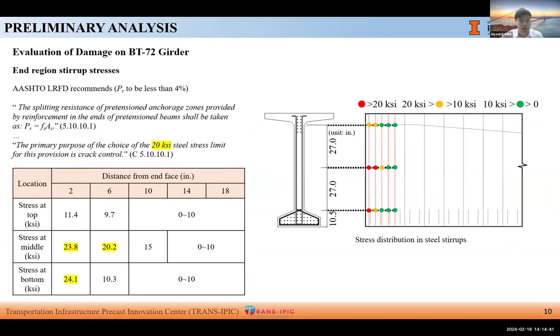The stress distribution along the vertical reinforcements at end regions was also evaluated to see if BT72 girder satisfied AASHTO guideline. Although the bursting resistance was satisfied with showing 2.1%, which the code is saying 4%, the outermost stirrup exceeded the value in the middle and bottom of the girder with values of 23.8, 24.1, and 20.2 KSI.